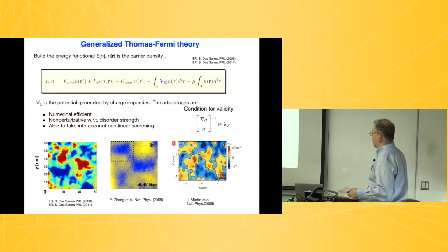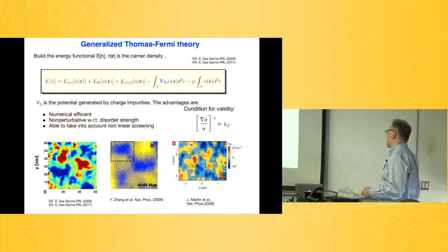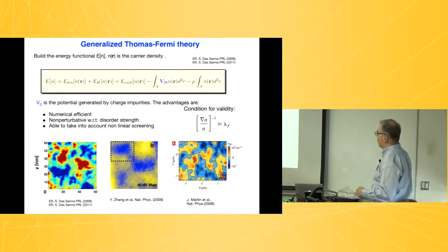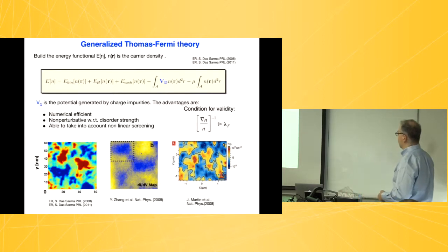And so these are just to visualize. So this is, for example, for a single disorder realization, the result of our calculation, and these are the results that were obtained using STM years ago by the group of Crommie in Berkeley. This is one of the first papers that was published on this issue, just showing that you do have electron-hole puddles, but the resolution here is micron, so this is not really helpful to be quantitative. But here you can see that you really have these electron-hole puddles that are of the order of tens of nanometers in size.